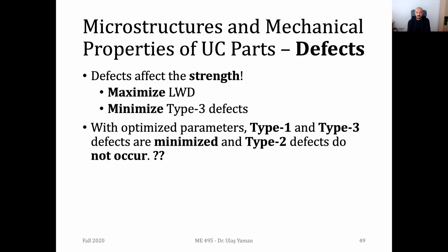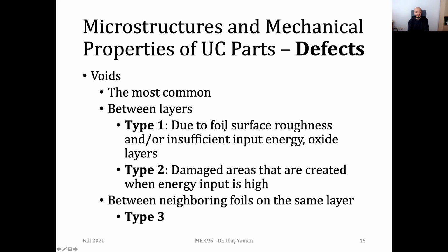So once you optimize your parameters, you can somehow decrease or maybe totally eliminate type 1 defects and type 3 defects. They can be minimized, but if you have fully optimized parameters, we can totally eliminate type 2 defects. Why do you think that is? We don't have full control on type 1 and type 3, but we can totally get rid of type 2 defects if you have optimized parameters. So what do you think? Let me go back to the definition of these types. We are stating that type 1 and type 3 can be decreased once you have optimized parameters, but we can eliminate type 2 totally. Can anyone comment on this?